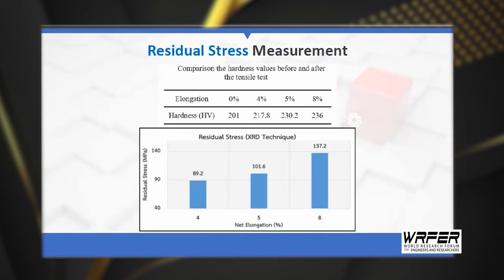Then we test by measuring the hardness before pulling and after pulling the workpiece. The range of hardness measurement is within the gauge length obtained from the calculation. The workpiece increases its hardness due to the strain. It also results in residual stress, with the sheet workpieces having elongations of 4%, 5%, and 8%. Then the tensile-tested workpieces are taken to measure residual stress by the XRD technique as a benchmark for calibrating the signal values obtained from the BHN system.